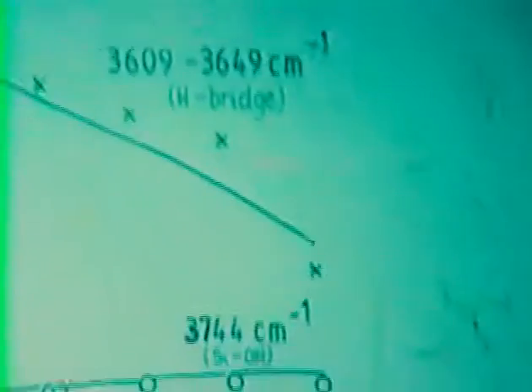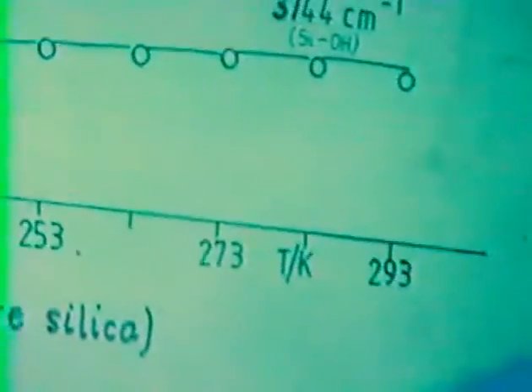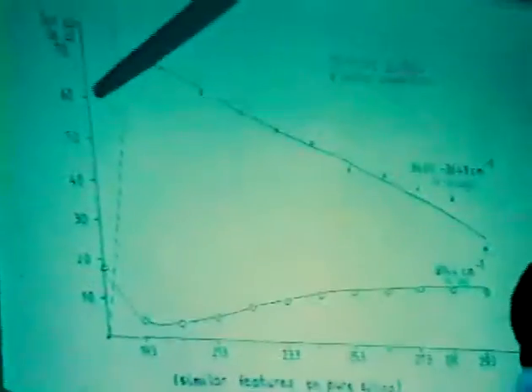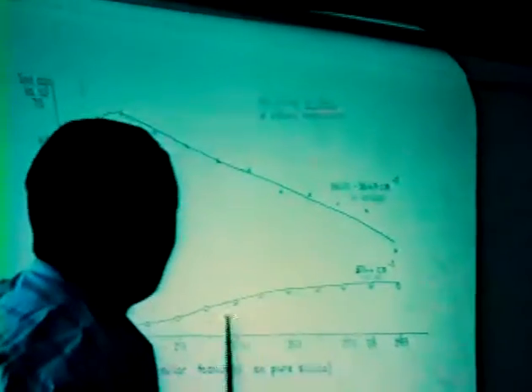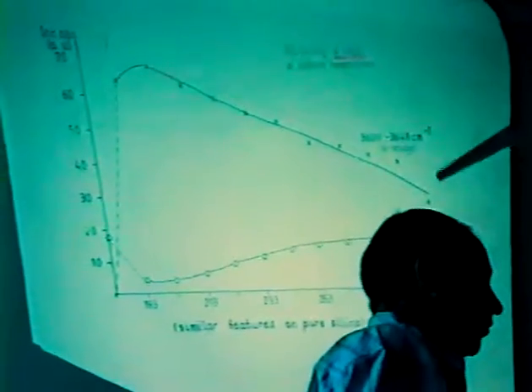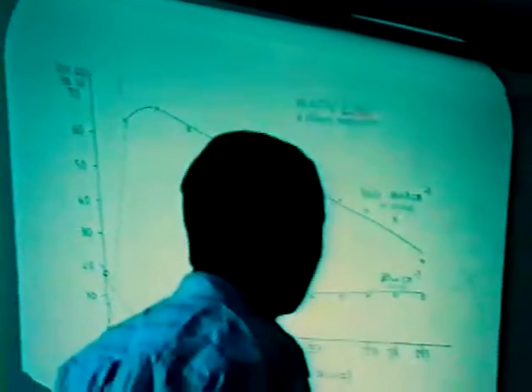After the pretreatment applied in our experiment, a sharp and intense band at 3744 wave number remained on the spectrum, which is characteristic for silanol, SiOH, on the silica. When methyl chloride was added to this sample at low temperature, the intensity of this band went to the minimum, and a broad absorption at the low wave number side of this band built up, which is characteristic for hydrogen bridge bonding species. Very interestingly, at the end of our experiment, when this broad absorption had been removed, either by evaporation or any other treatment, the intensity of the silanol group hadn't reached its original value.